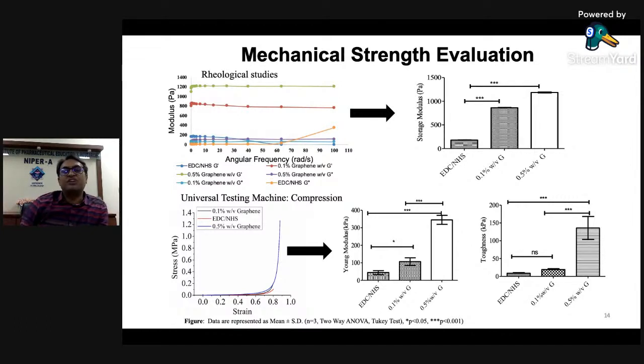In the rheological studies, you can see the storage modulus of 0.5% graphene is significantly higher, which shows the material is, first of all, very spongy, as well as has a good gel-like material, having sufficient strength.